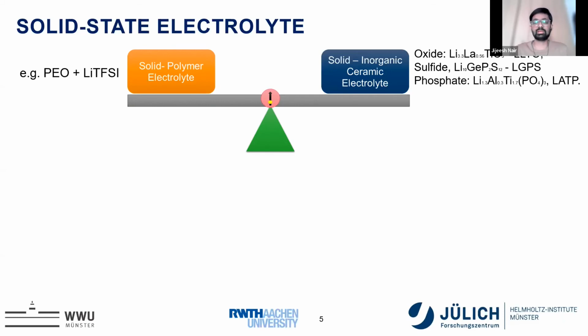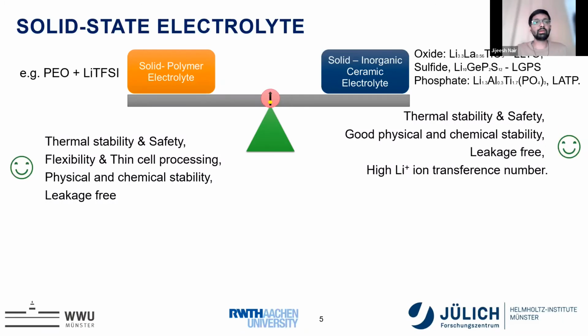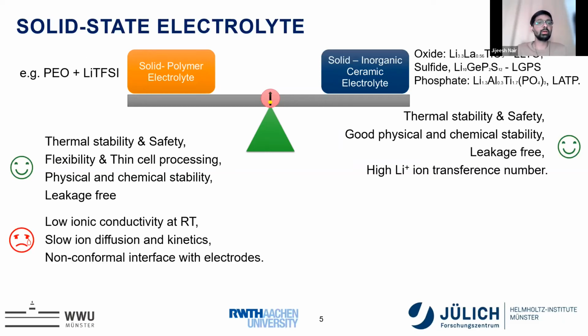oxide, sulfide, phosphate, etc. So if you look at the polymeric side, it can be thermally stable, safe, and flexible, which is one of the advantages. We can produce thin batteries, and physically and chemically, as polymers are comparatively much more stable, their melting point and thermal stability are higher, and as no solvents are used, they can be leakage free. But they have big issues like low ionic conductivity at room temperature. The lithium ion mobility inside is slow, with slow ion diffusion and kinetics, and a non-conformal interface with the electrode, because if we use the standard conventional processing of